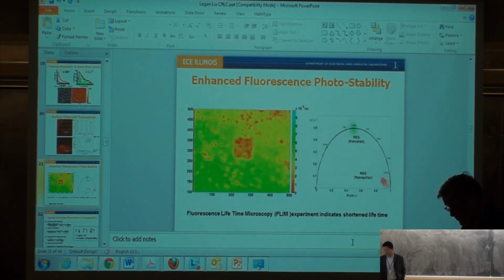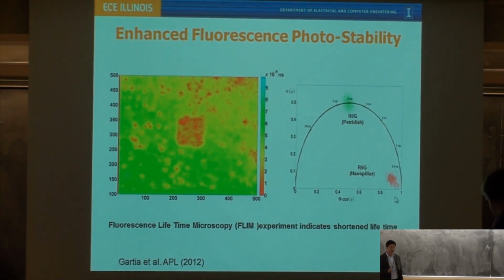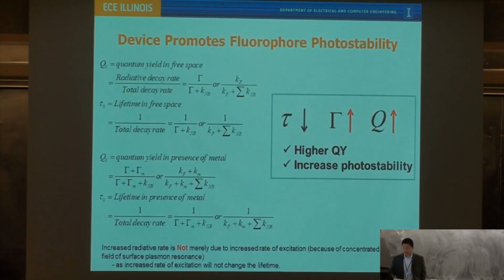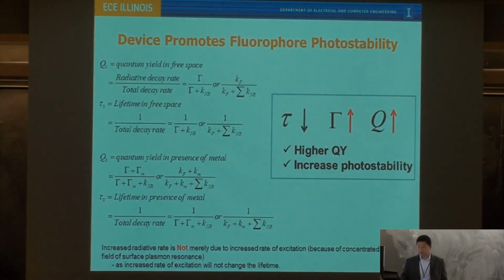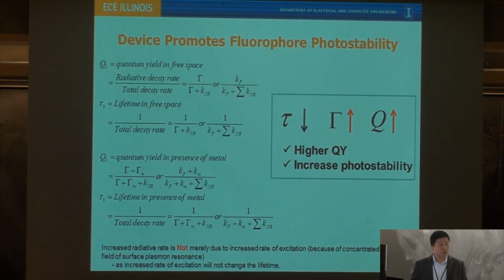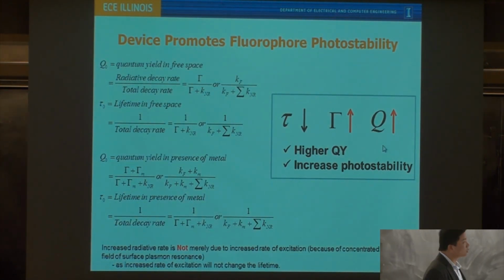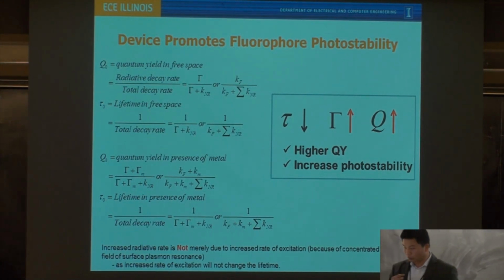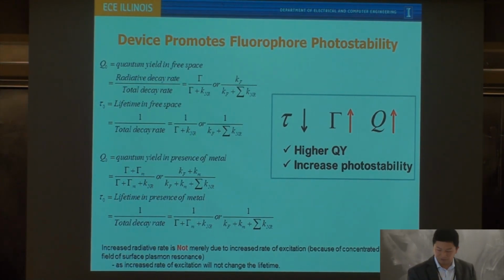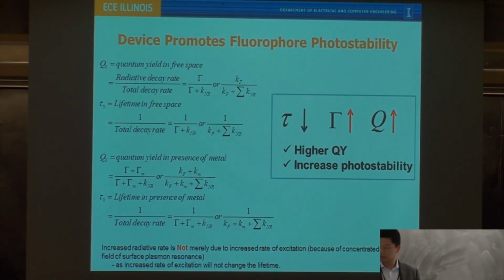If you go to the paper, there's a paper in APR. This is the data we measured experimentally. If we trust this data, we then use it to calculate our radiative and non-radiative decay rate, gamma, and then use that to calculate our quantum efficiency Q. So here we actually see both a change of the radiative decay rate as well as the non-radiative decay rate in our case, based on our measurement.